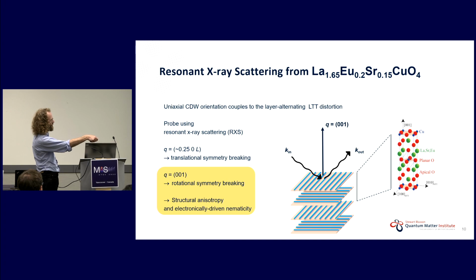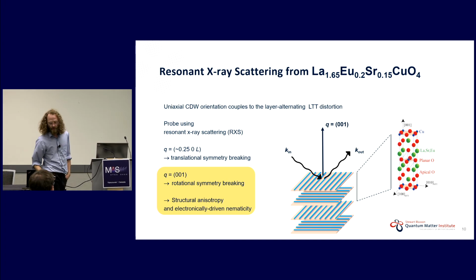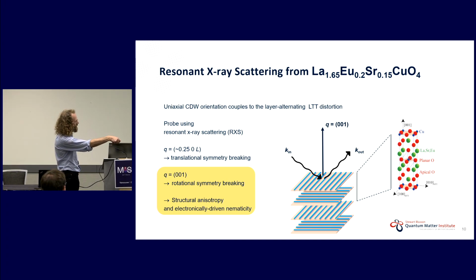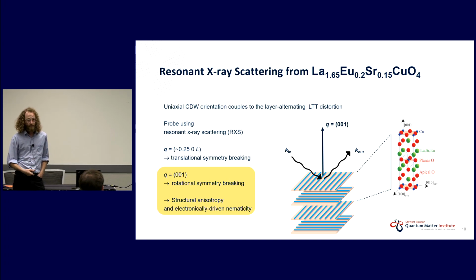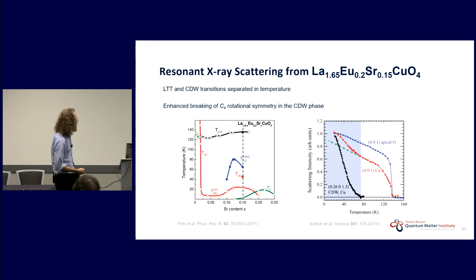So we're going to look at, for example, the apical oxygens, which should be purely associated with the structure, and then compare that with signals we see using the copper L3 resonance or the planar oxygen K resonance, which have additional sensitivity to the copper oxygen planes. Okay, so here we go.